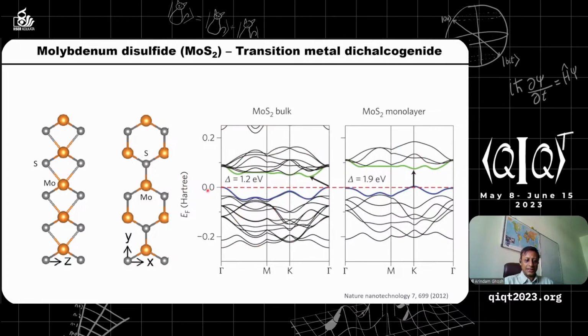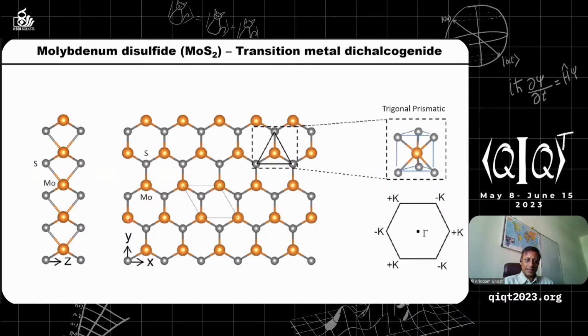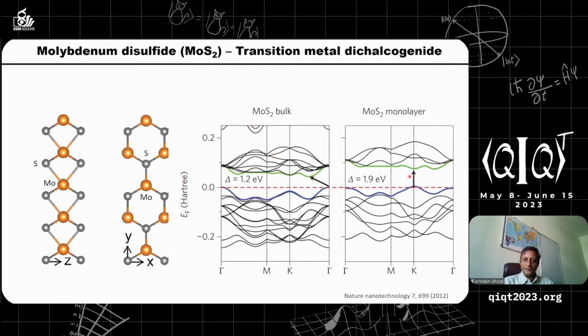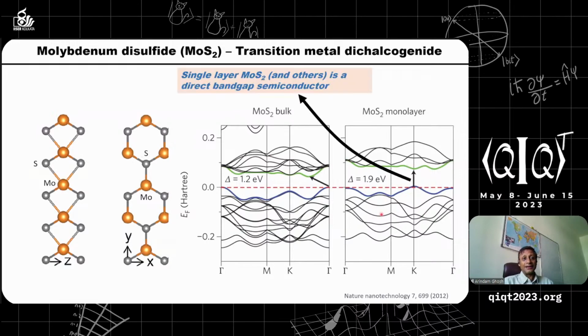Okay, it looks hexagonal, but molybdenum and sulfur from the top looks something like this. It's a trigonal prismatic structure. Because of this unique molybdenum and sulfur orientation, molybdenum disulfide is a semiconductor, very similar to silicon, except that silicon is an indirect bandgap semiconductor. But in the case of single layer molybdenum disulfide, it's a semiconductor with a bandgap of about 1.9 electron volt. And this makes a wonderful optoelectronic element.